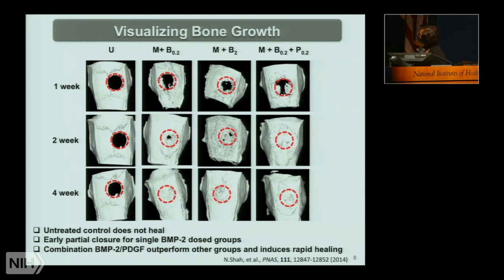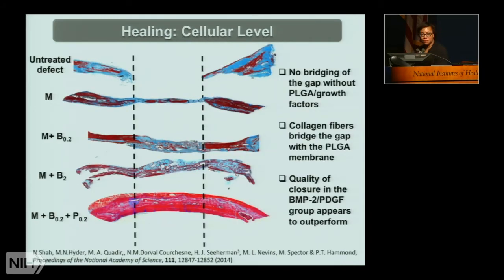However, when we look at 0.2 micrograms of BMP2 and 0.2 micrograms of PDGF, with micro-CT, we see perhaps a sign that there's somewhat more rapid healing, but we can't really tell what's going on with the bone until we look at the histology and do mechanical measurements of the native bone and really examine what is being generated here. So here you can see cross-sections from histology of the untreated defect, in which we have this gap that remains, and the margins of the bone.